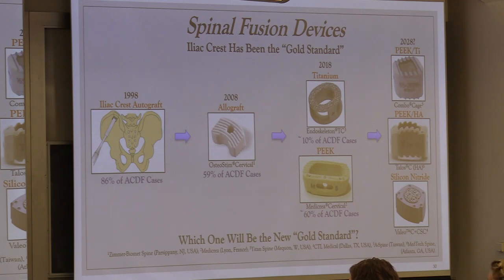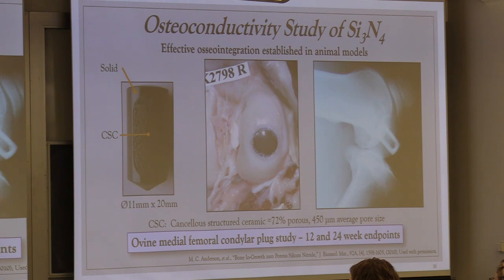And in fact, that's where I'm going next, is to just basically show an early study which actually originated here at the University of Utah in the Bone and Joint Research Laboratory, where we wanted to find out how good is silicon nitride in terms of its osteoconductive behavior. So the study actually involved taking a silicon nitride bone plug here, which was a composite of a dense outer portion and a porous inner portion. The porosity on this material, which we called cancellous structured ceramic, was about 72% porous. And it had an average pore size of about 450 microns. And this was then implanted in the femoral condyle of mature sheep, and they were ambulated for up to 3 months or so, and then 12 and 24 weeks.